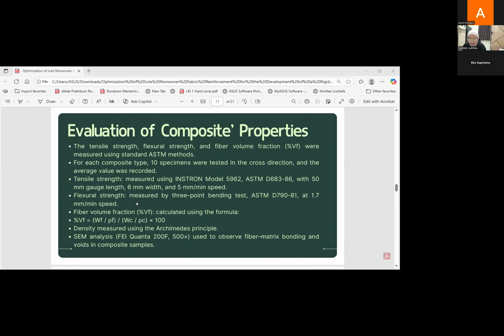So the next is the evaluation in this paper. They use 3 evaluations: tensile strength, flexural strength, and fiber volume fraction, following standard ASTM methods. For each composite type, 10 specimens were tested in the cross direction, and the average value was recorded. Tensile strength was measured using the Instron, the flexural strength by a 3-point bending test, and fiber fraction calculated by this formula.